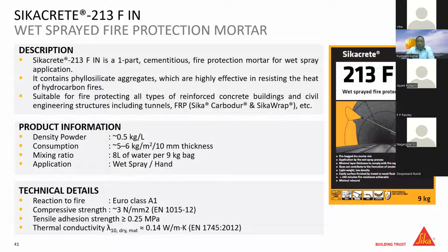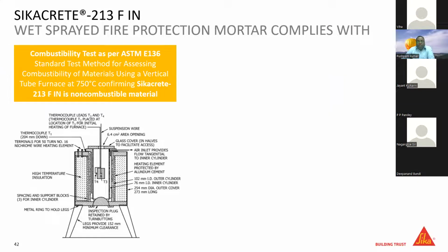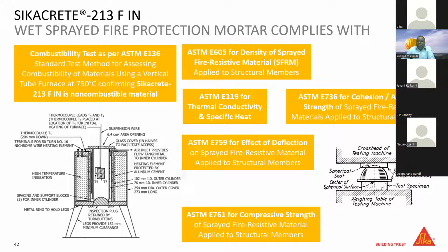This fire protection mortar has certain properties: the reaction to fire should be Euroclass A1, and it should have defined thermal conductivity and tensile adhesion strength with the concrete section as per the various codes. This product is tested as per ASTM, and there are clear guidelines, especially for the non-combustibility test as per ASTM E136, wherein the specimen is exposed to a fire of 750 °C and checked that it should not have any impact from the high temperature of 750 °C. So the test is done to ensure the mortar is non-combustible in nature. In addition, there are various other tests, like the density test, cohesive bond test, thermal conductivity test, specific heat test, deflection test, and compressive strength test.